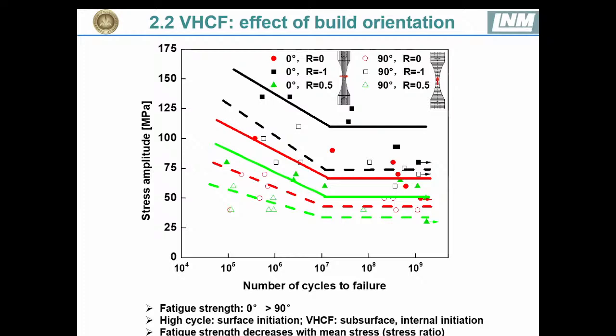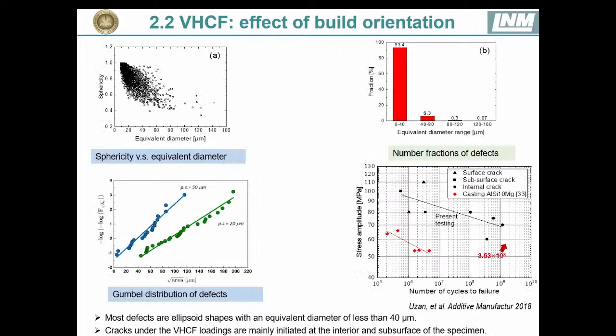This is also in general with the common practice, and also both surface and subsurface, that is the internal crack initiation, will be shown for these specimens here. And the sphericity and the equivalent diameter of the cracks are also shown here. And we can see that the sphericity of the defects decreases with the equivalent diameter. And most defects are ellipsoid shapes and with equivalent diameter of less than 40 microns.